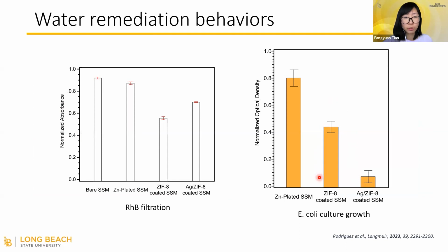And when we compare the performance of the ZIF-8 and silver incorporated ZIF-8 membrane, we found that in both cases, the absorption for Rhodamine B is similar, but the silver incorporated ZIF-8 coated stainless steel mesh has a very strong antimicrobial property. Almost 90% of the bacteria, we use E. coli, died. And this E. coli culture growth study was done in Dr. Banderi's lab.